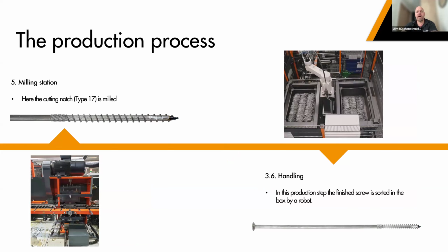You might know this type 17 tip, which has the so-called cutting notch. For this type, the screws are always fixed, and a little saw blade mills out the notch, which is known on many screws. The other tips, like the drill point tip, get punched or pinched at a different machine. But by this, we always end with a partially threaded screw on the standard machine.